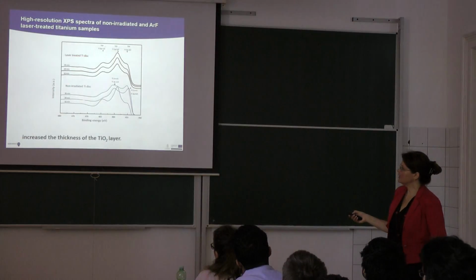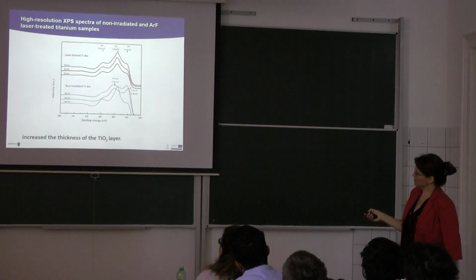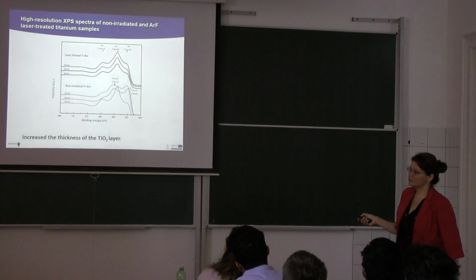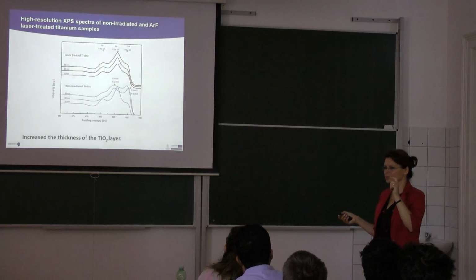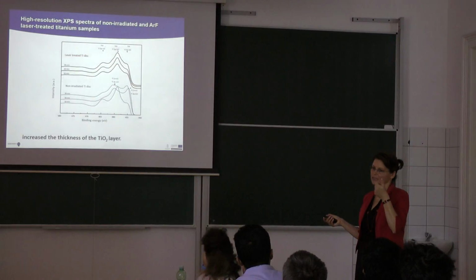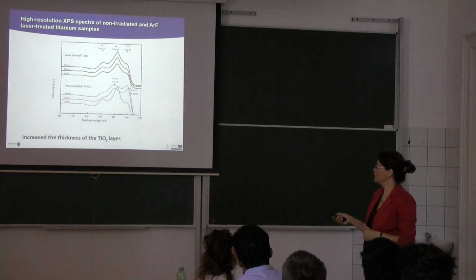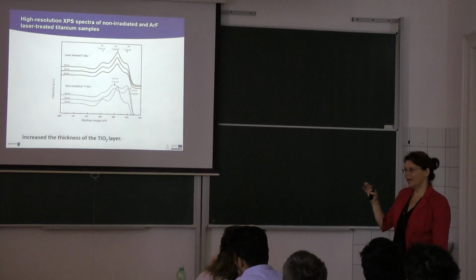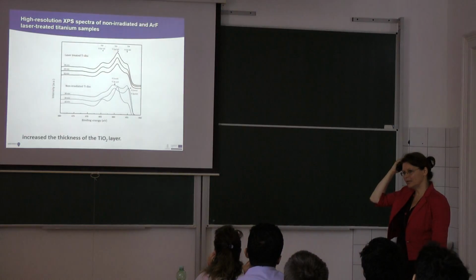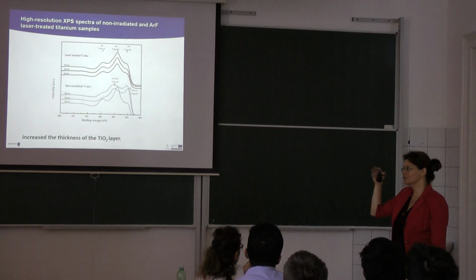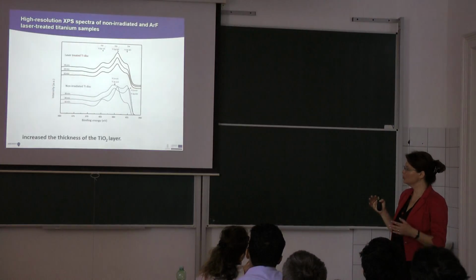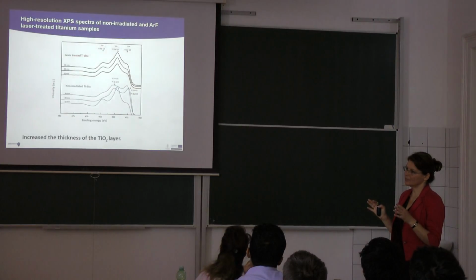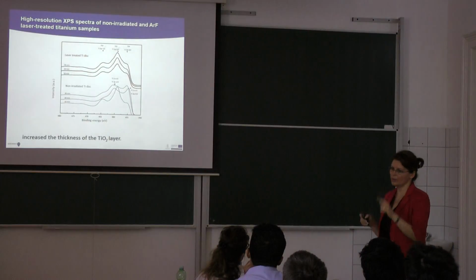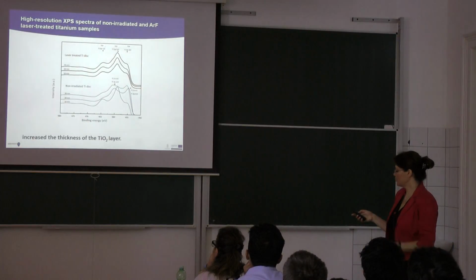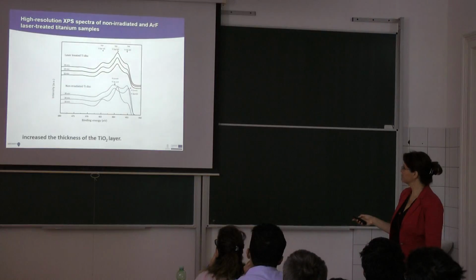And for the non-irradiated titanium disc, this metal will come out very quickly. So therefore, we could show that the titanium dioxide layer was three times larger in the case of the laser-treated sample. At that time we saw that this is good, but then other researchers showed that the good thickness of the titanium dioxide layer is the native one, around 20 to 100 angstrom. But it was a nice result.